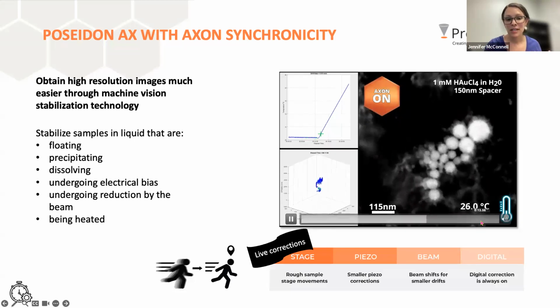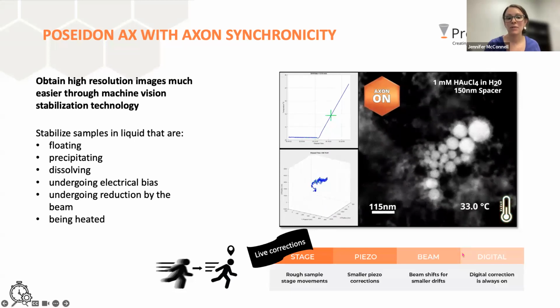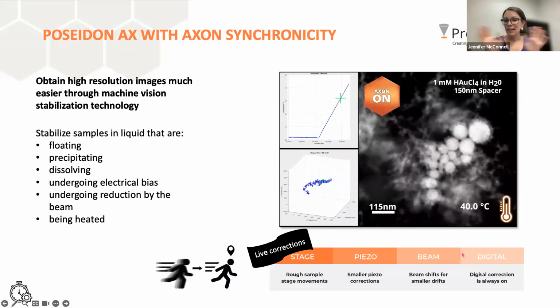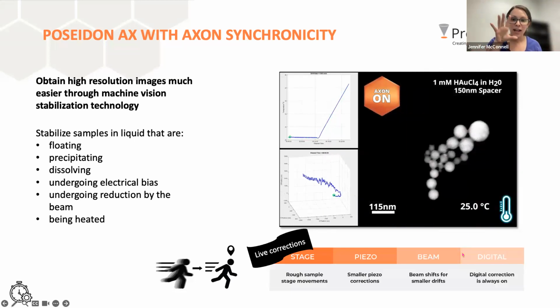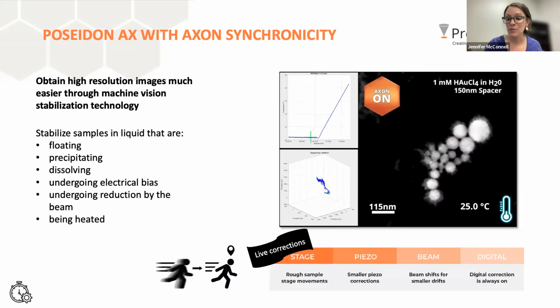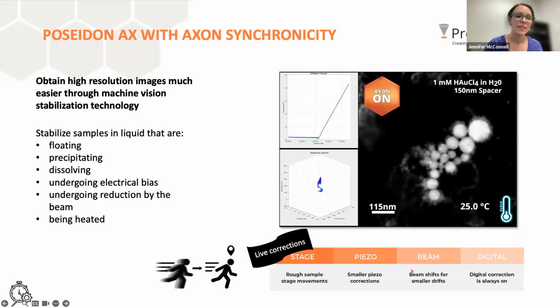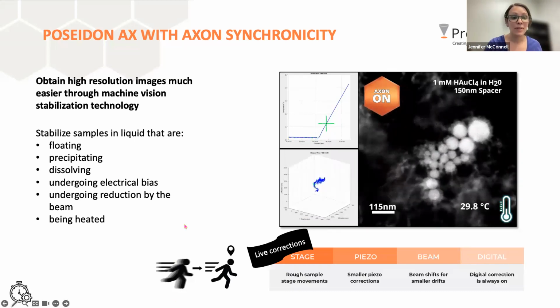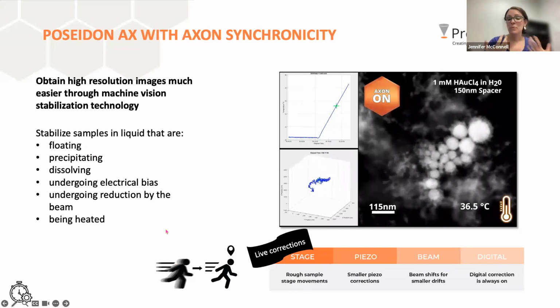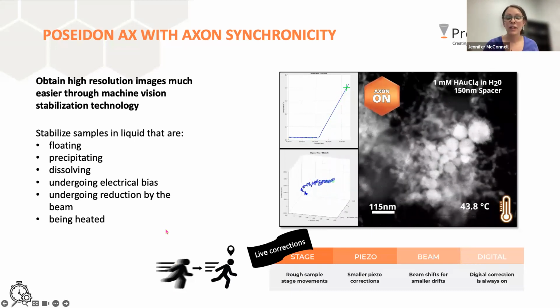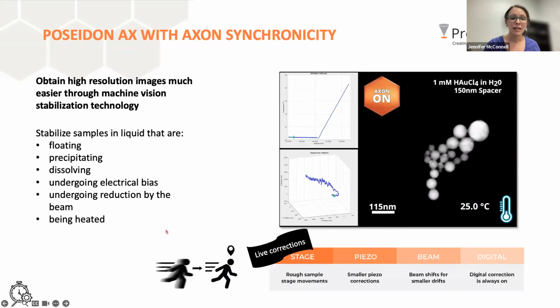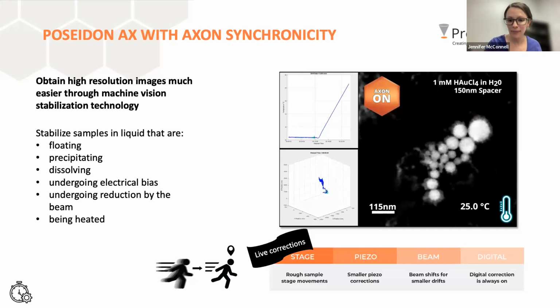So you see the growth starts here, and then you can see the temperature ramp kicks in, and we start heating. And despite all the chaotic dendritic growth and such, everything is stabilized and still. And again, that's what you see as the microscopist at the TEM, and you don't have to do anything to achieve that. And it's all happening live, but whether it's floating, something's precipitating, dissolving, undergoing electrical bias, reduction by the beam, or being heated, it can control movement for everything that might happen in an in situ experiment.